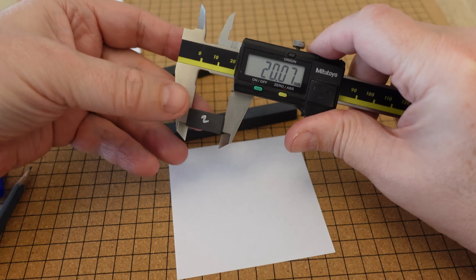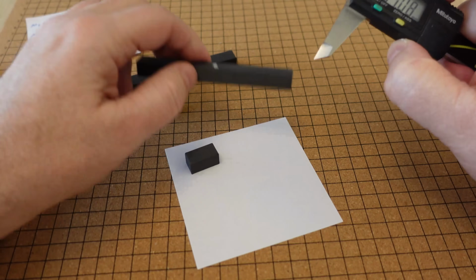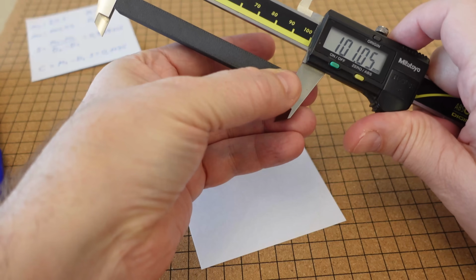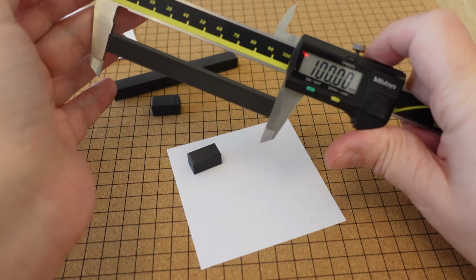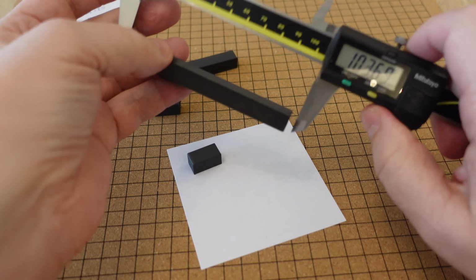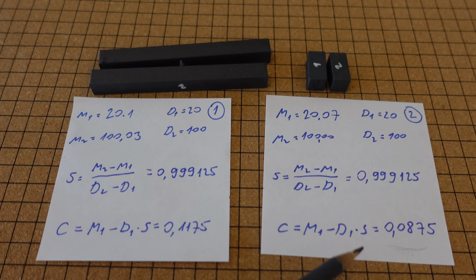And this calculation is finished too. Absolutely no changes on the scale factor, exactly the same value, but what is more important is the C constant offset, and in this case we can see that we could reduce it with this drying. It is much closer to the 0 now, but even this was quite dry, so I'm not sure why that oozing appeared, but now definitely it is dry and ready for the test objects.